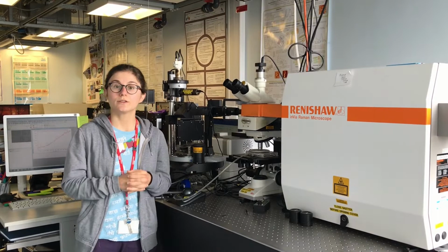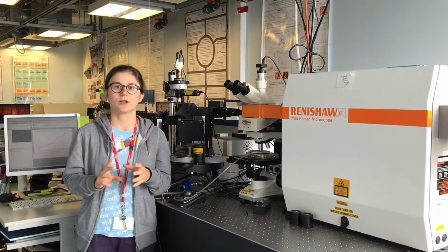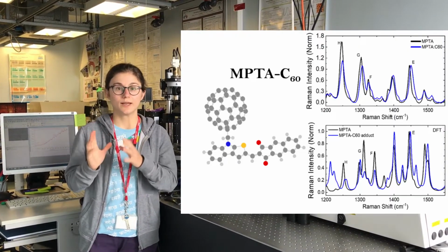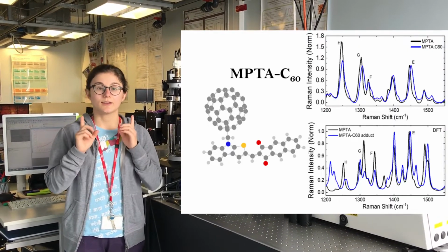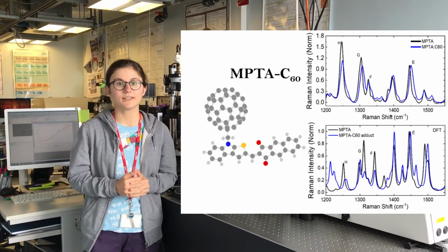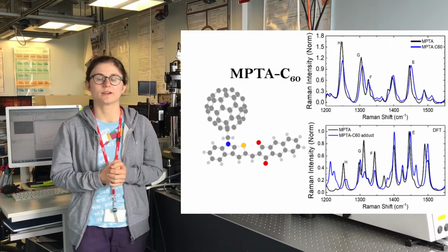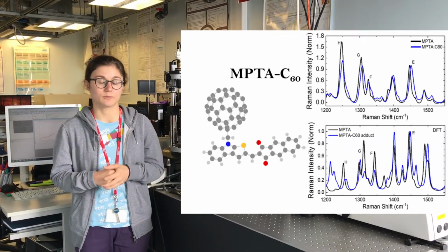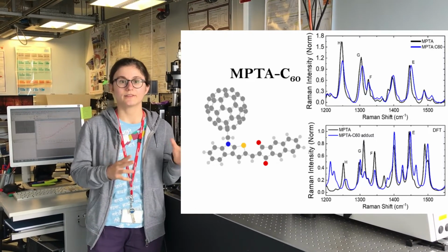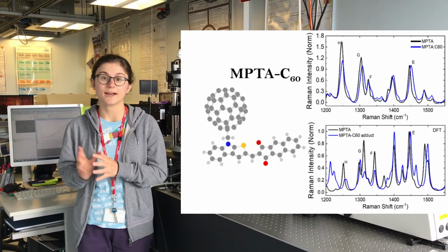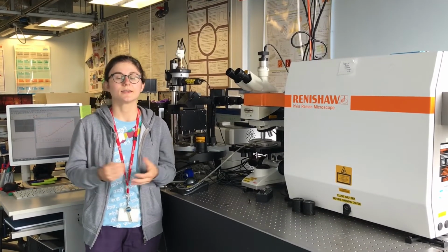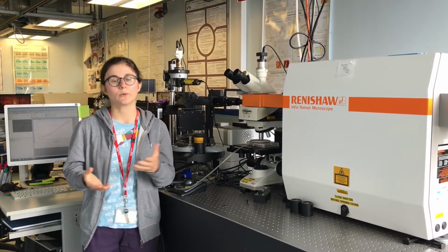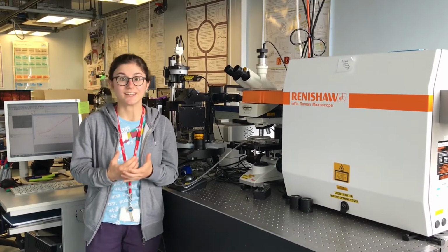But we also need to consider the second factor, which is the potential creation of chemical compounds with the fullerene. For the planar molecule, we can have this reaction, and the Raman spectra of the adduct, the complex with the fullerene, are partially compatible with what we actually observe in the Raman spectrum of the blend. So we think there is both the aggregate presence and the presence of adduct. Now we want to understand if this has an impact on the energy level and the trap states, so we need to move to the energetic characterization.